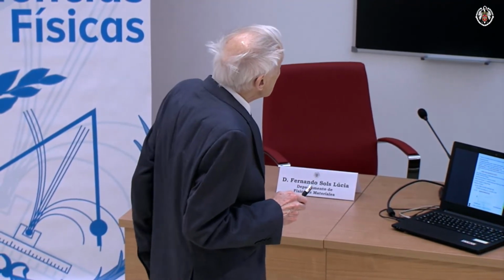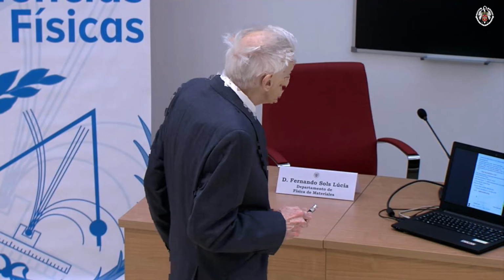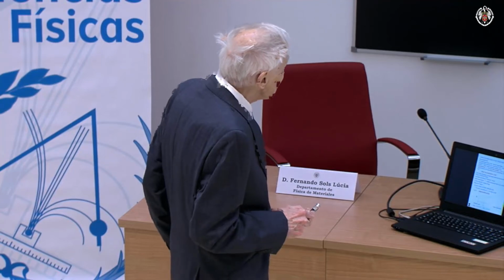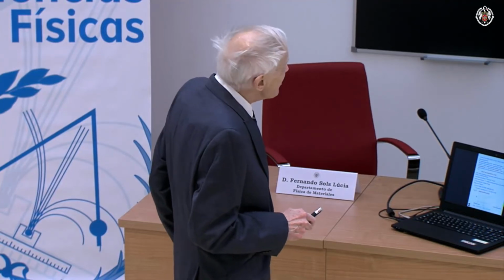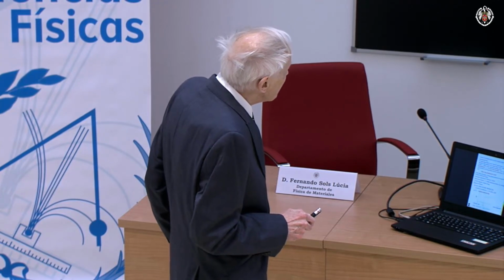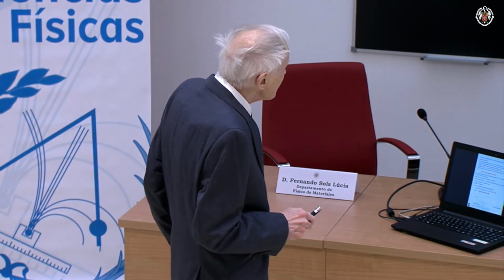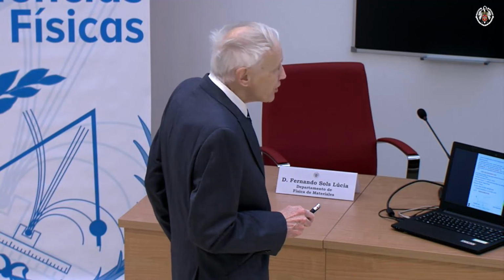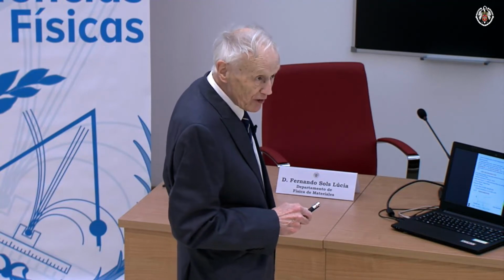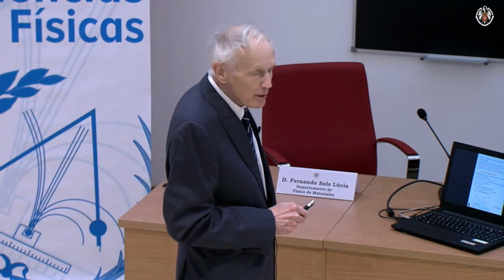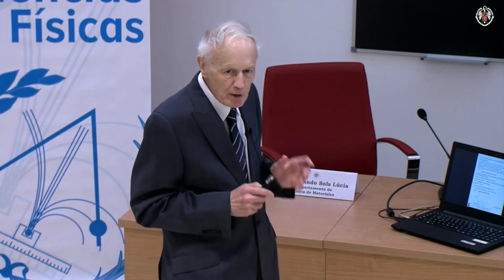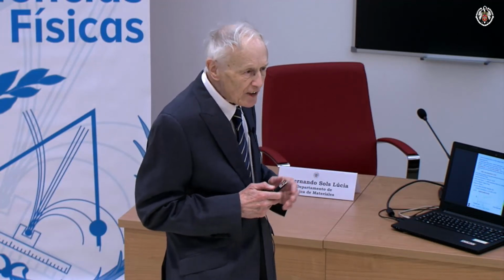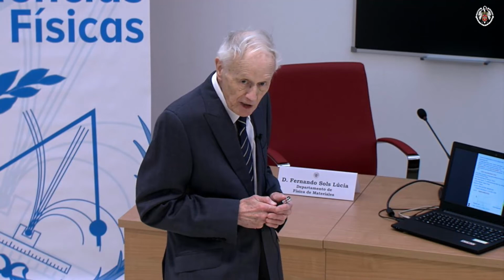Alas, there's one slight problem. In most materials, resistance drops to zero at Tc, but Tc is only about 1.3 degrees absolute. That's about 1/300th of room temperature. So you can get there, but it requires a lot of special apparatus and so forth. Not terribly good for practical applications.